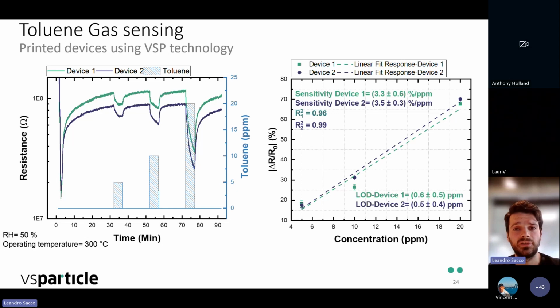So essentially, with this kind of experiment, you can extract the calibration curve of your device in terms of the response. So we compare the resistance at the baseline and at the maximum response of our device. On the right, we can obtain the calibration curve of the device responding towards toluene, and we did this with 2 devices. So you see device 1 and device 2.